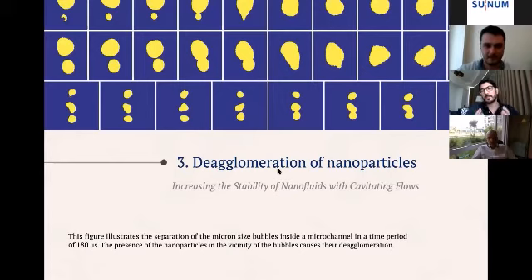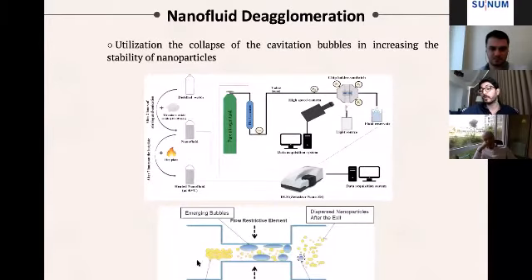So up to here, I tried to state the physics of cavitation according to some parameters that we are studying in our experiments. Now we can use this huge database and knowledge in different applications. For example, in the deagglomeration of the nanoparticles, we use the cavitating flow to increase the stability of the nanoparticles and also to deagglomerate the nanoparticles. For example, the agglomerated nanoparticles are introduced to the restrictive elements or microchannels simply. The cavitation bubbles are generated inside the microchannel, and by collapsing the cavitation bubbles, it is possible to disperse the agglomerated nanoparticles in the extension part.